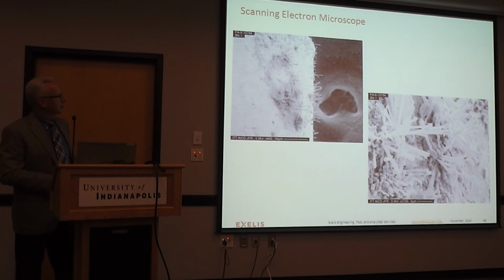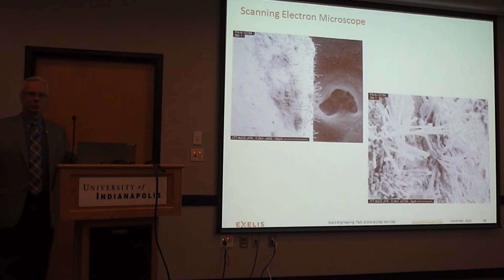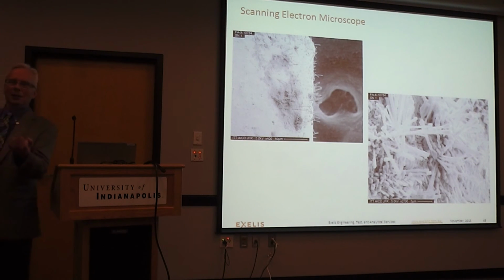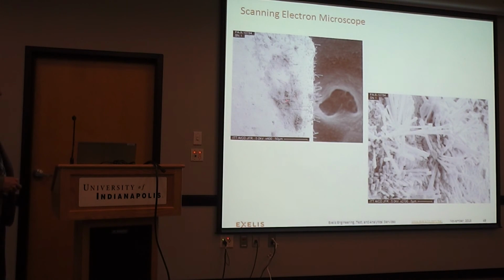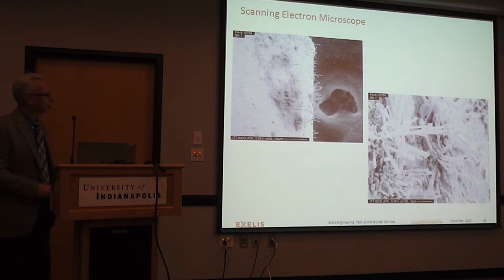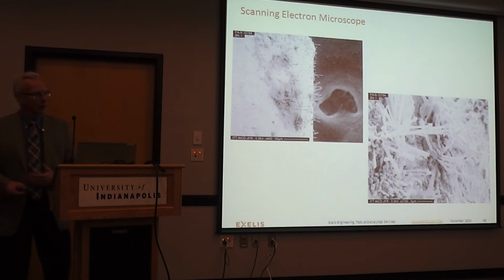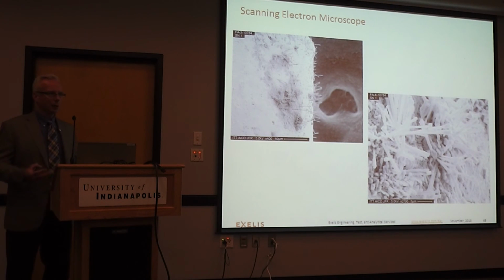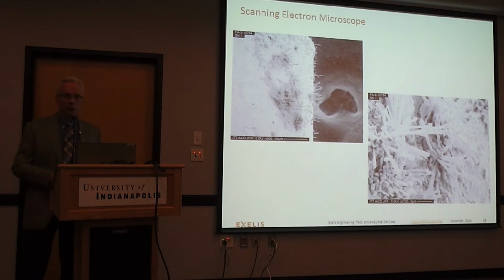Now this looks like a chia pet, but what that actually is is a silver-plated terminal. It looked dirty, and the inspector brought it to us and said, hey, this spaceflight terminal is dirty. What is that? We put it in the scanning electron microscope, and we found these little filaments growing out of the surface. We analyzed those using energy dispersive spectroscopy, and based on the elemental composition, we determined that it was most likely the result of plating salts, not thoroughly rinsed, left behind on the plated surface, and the presence of those salts and residual stress in the deposit causing this crystal growth to occur.